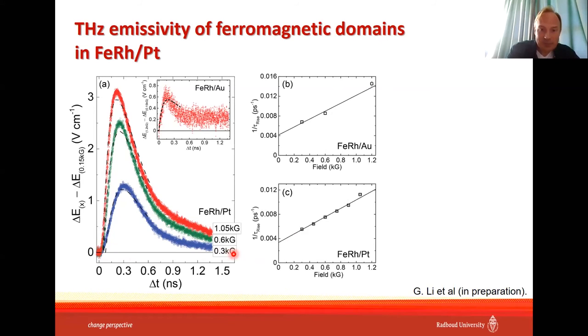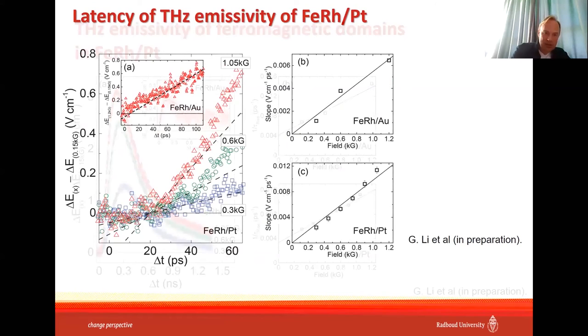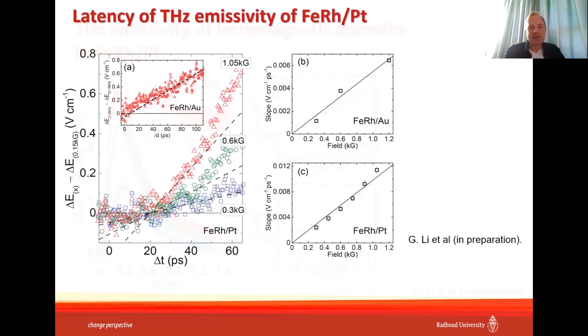and the dynamics depends on temperature and on magnetic field, but what's most important here is the magnetic field. As the magnetic field increases, it becomes faster and faster. Then what was the most surprising for us is that if you zoom in at the short time scale, there's quite a latency period of 20 picoseconds when the nuclei generated by the first pump in iron rhodium do not emit THz radiation at all. So there is no THz emission up to 20 picoseconds.